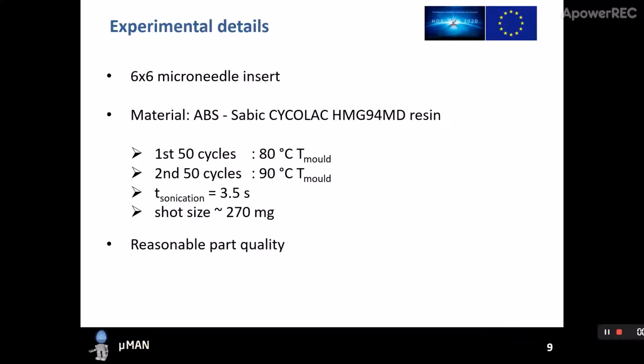Here are some of the experimental details. We use this 6x6 microneedle mold insert, and an ABS resin as our polymer material. In the first 50 cycles, we used a mold temperature of 80 degrees, and in the second 50, we increased it to 90 degrees Celsius. We used a sonication time of 3.5 seconds and set a shot size of 270 milligrams. All of these experimental parameters resulted in reasonable part quality, which will allow us to see how the process fingerprinting will work in the first place.